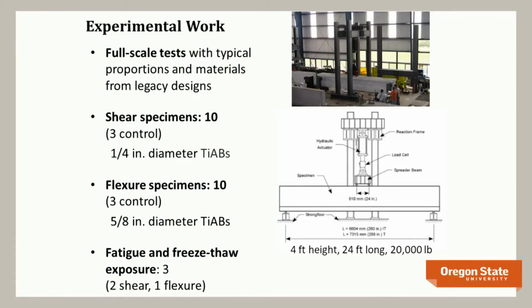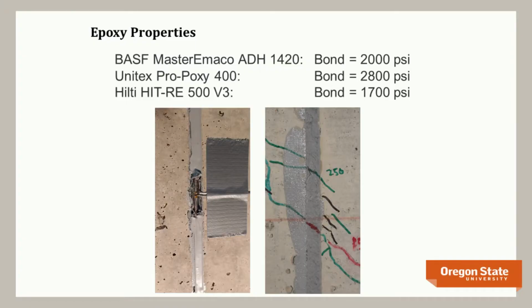Our typical specimens weigh about 20,000 pounds, right? They're 4 foot high, which is a typical size for these girders, and about 24 foot long. We've used a number of different epoxies over time because epoxies change. Bond strength is probably the most useful characteristic. And you can see our bond strength, the one with the highest bond strength is actually the worst epoxy.